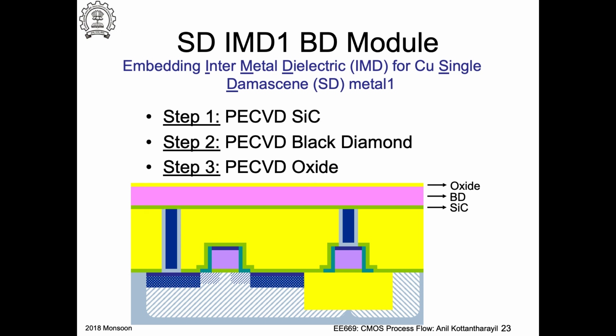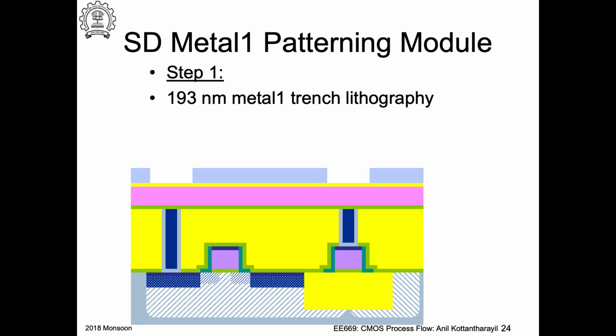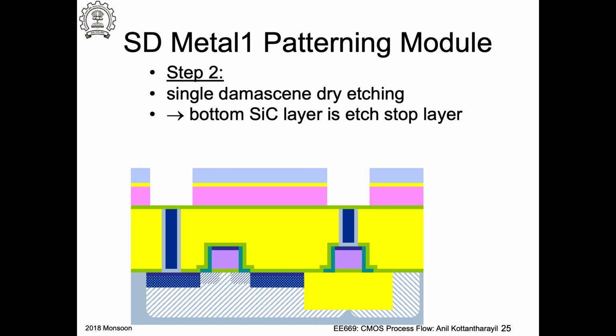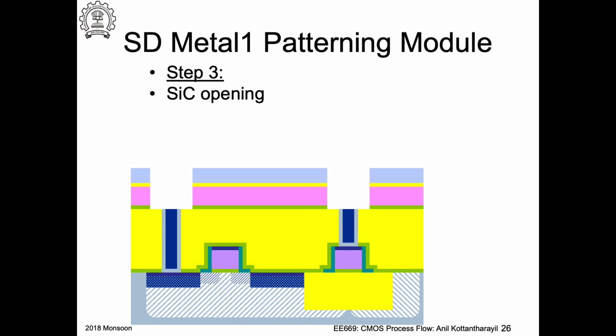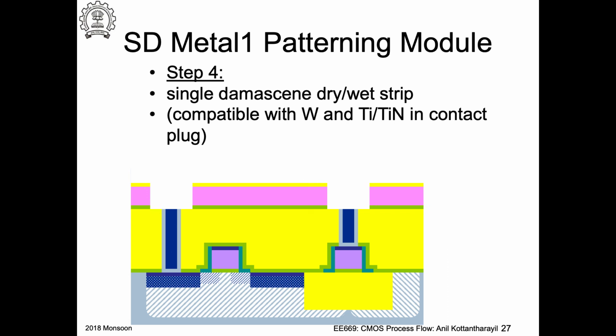Okay, so now we'll continue this. So we have this PECVD black diamond and the PECVD oxide deposited on top. Okay, looks like this, right? And then you're going to do lithography, and then you're going to etch these layers. Okay, so silicon carbide is used as an etch stop layer, and then silicon carbide is opened, and then you do what is called a stripping. Essentially, the top layer is photoresist, right? So you would actually remove that. Okay, and then you are going to do something. So now what do you have? You have your tungsten plugs exposed, right? And you put some dielectric on top.